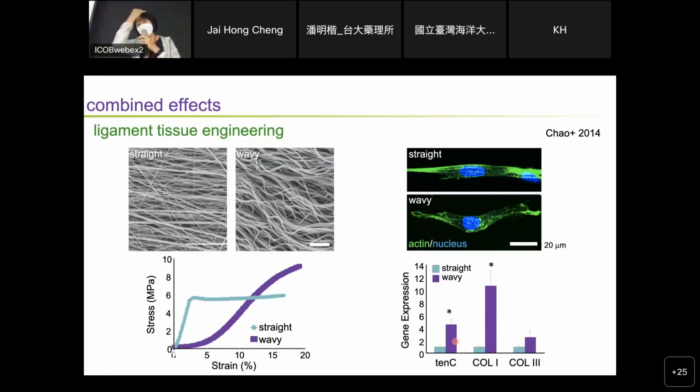humans and in animals. So we use a technique called electrospinning and use polymers basically to generate these fibers. We can make them straight and aligned, and with some processing, we can make them wavy. A professor in chemical engineering said it's basically like perming your hair. You can make your hair wavy, you can make your fibers wavy. So with these wavy structures, you can see in the EM pictures, we can find that there's a corresponding change in mechanical property.